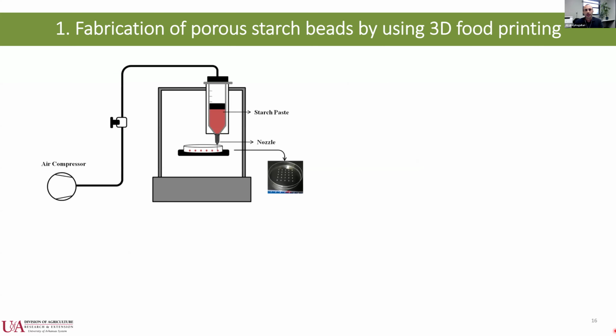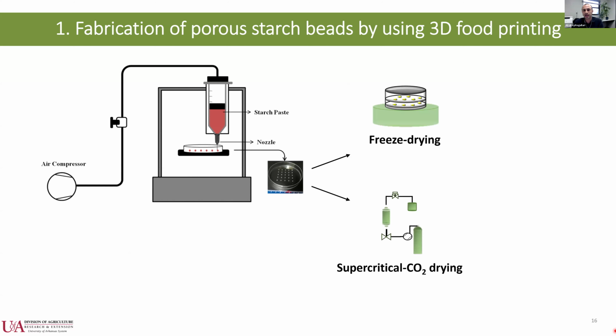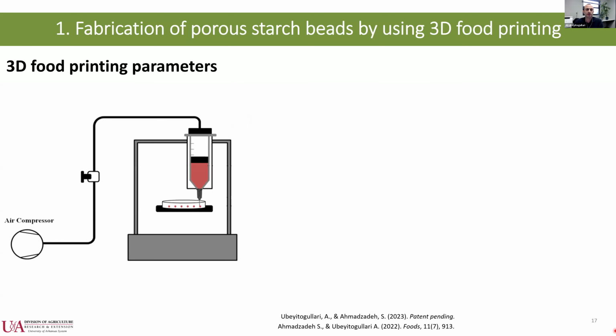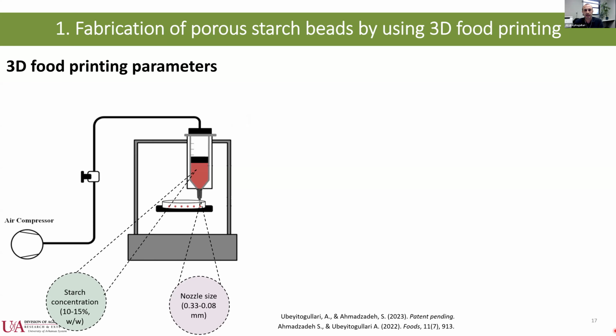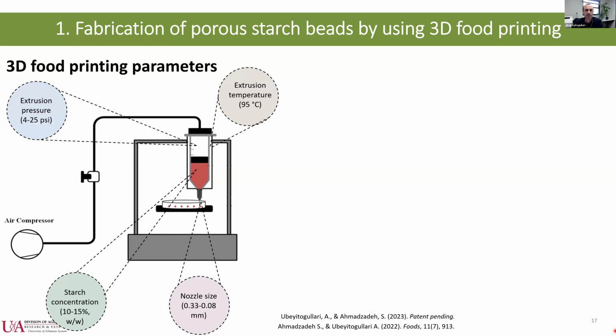So in the first study I will share, we looked into an extrusion-based 3D printer, and here we load basically the starch paste in a cartridge, and we dried the particles using freeze drying, and then we also looked into supercritical carbon dioxide drying. So in terms of 3D printing parameters, we looked into nozzle size. So we used different nozzle sizes here, different starch concentrations. Then extrusion temperature was constant, which was due to looking into starch gelatinization. And then we used different pressures for extrusion.